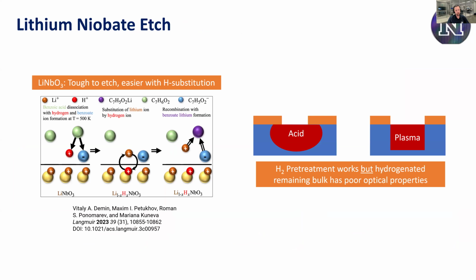The way people have done this historically is they would just take the lithium niobate and boil it in acid. Now, the problem is that hydrogenation makes a different kind of material. It's not really what you want. It's not as good as real lithium niobate. And that bulk hydrogenation, or even a pre-treatment in plasma, is not so great. It's hard to control the depth of it. So this isn't ideal, but it does give us an idea. What if we did a cyclic modification? Maybe we could hydrogenate just the surface in each ALE cycle and then remove that hydrogenated layer.